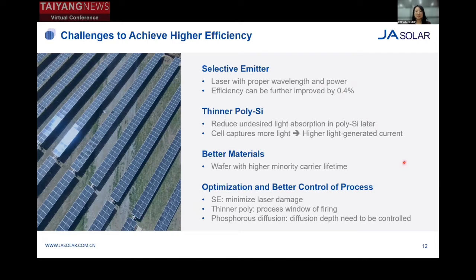The second one is thinner polysilicon, which will reduce the undesired light absorption and allow the cell to capture more light, thereby increasing light-generated current. And the third one is better materials such as N-type wafer with higher minority carrier lifetime. It will reduce the recombination rate of the cell. And the last one is to further optimize the process. For example, minimize the laser damage in SE process. If we use a thinner poly, the firing process needs to be better controlled to prevent metal contact from going through the polysilicon layer. And during the phosphorus diffusion, the diffusion depth needs to be well controlled. It shouldn't pass the silicon oxide layer.